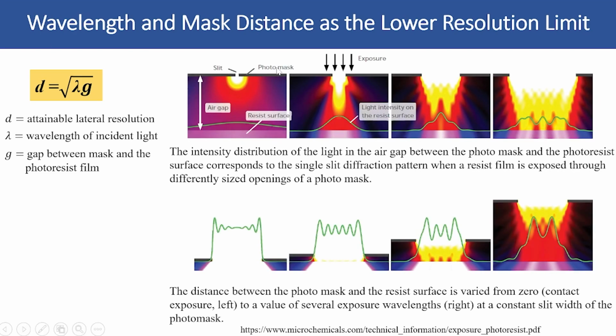The first is related to diffraction. It shows the diffraction of the light. As the size of the slit becomes smaller, the diffraction is more and more prominent. And this lower figure shows how, with the variation of the gap between the mask and the photoresist film, the distribution of the light intensity over the resist film changes. In the first case the gap is 0, and this is the distribution of the light, and as this gap keeps on increasing, the distribution of the light over the resist film changes. We see that as the gap is more, there is a more non-uniform distribution of the light as compared to the case when the gap is nearly 0. Hence it is very important to consider the gap between the mask and the photoresist film.